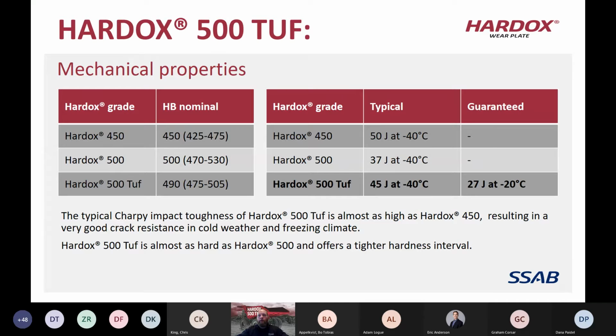Its nominal is 490 Brinell, but it has a tighter hardness range than a typical AR 500 plate. The typical impact toughness value for Hardox 500 Tuf is 45 joules at minus 40 C. And we actually have a guarantee on 500 Tuf, which is 27 joules at minus 20 C.